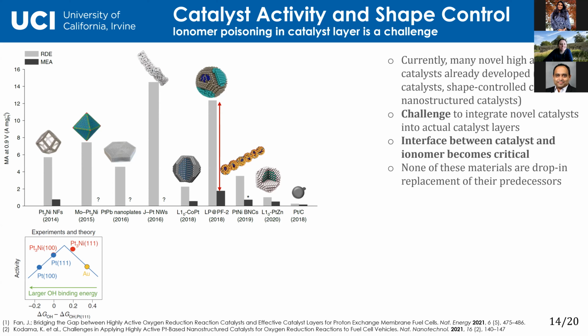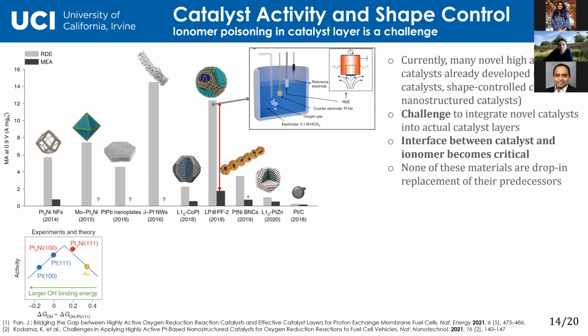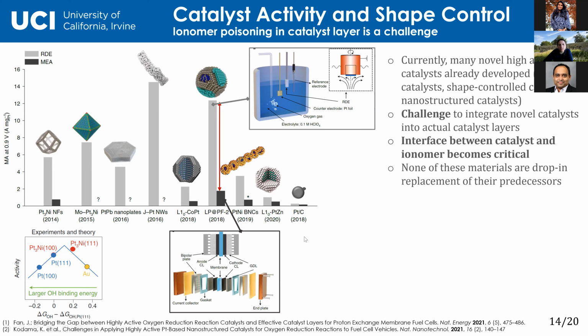So what you see here is the performance is amazing in RDE, right? You have huge mass activity. The moment you put them in an actual fuel cell, they don't work. Why? Well, in rotating disk electrode setups, typically you have working, counter and reference electrodes, you bubble oxygen, for example, for the oxygen reduction reaction, and you deposit a thin film on the tip of this rotating disk. In fuel cells, you make a catalyst layer, which is your catalyst, your support, your ionomer. You no longer have accessibility of acid. You rely on ionomer for transport. It's not as pure a system as RDE.